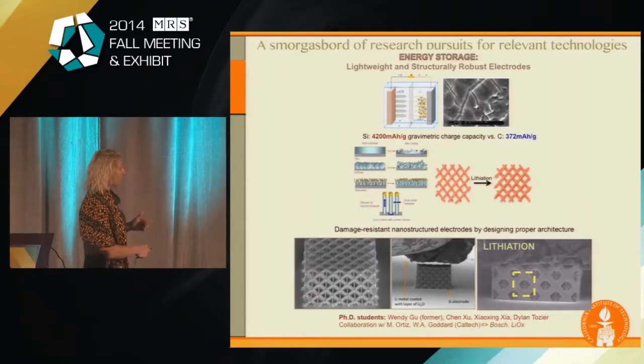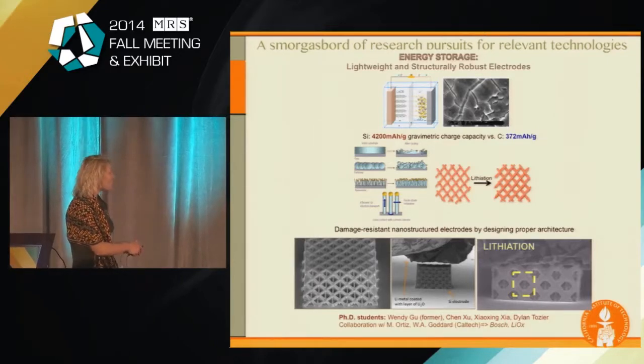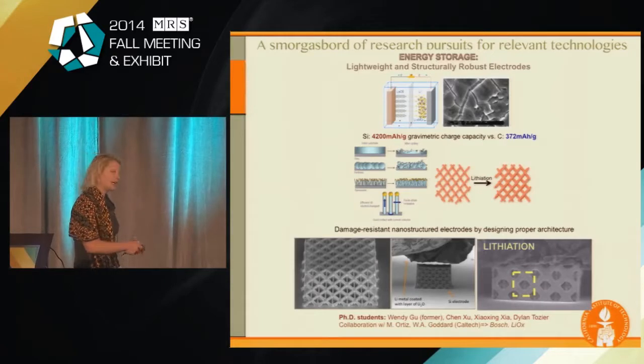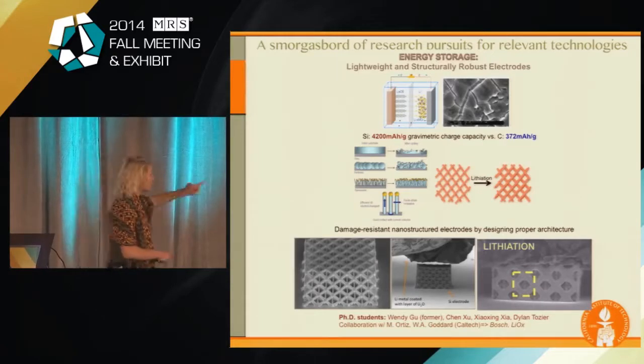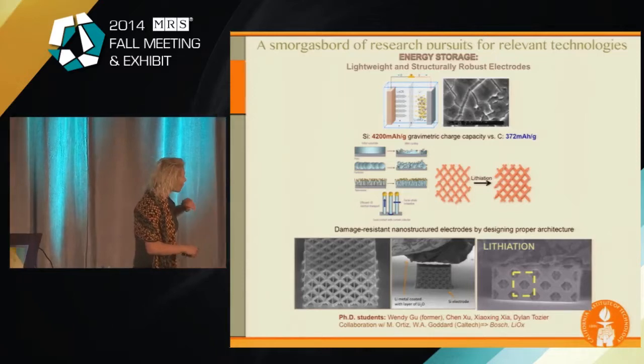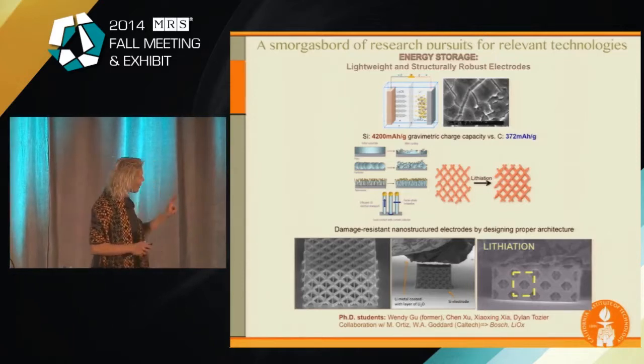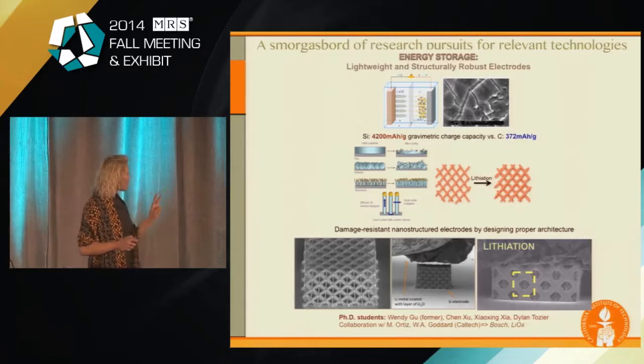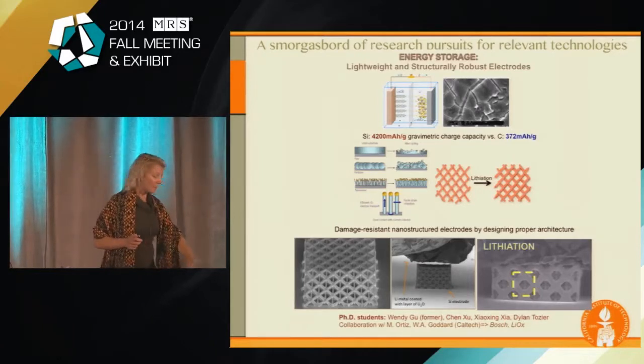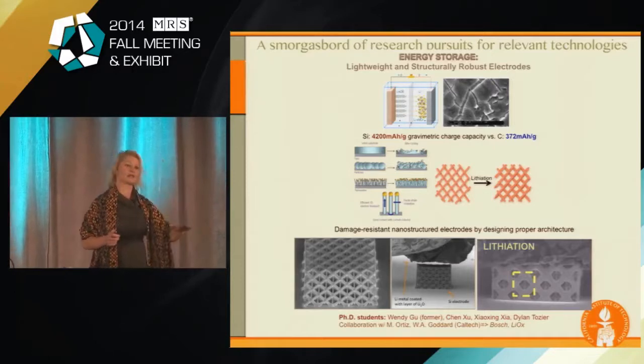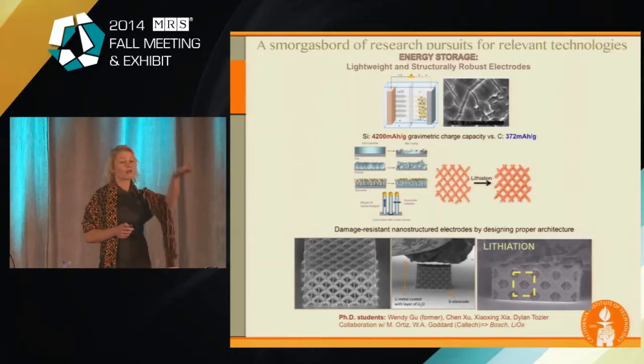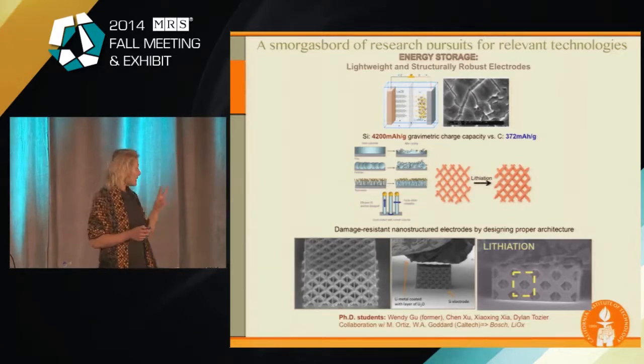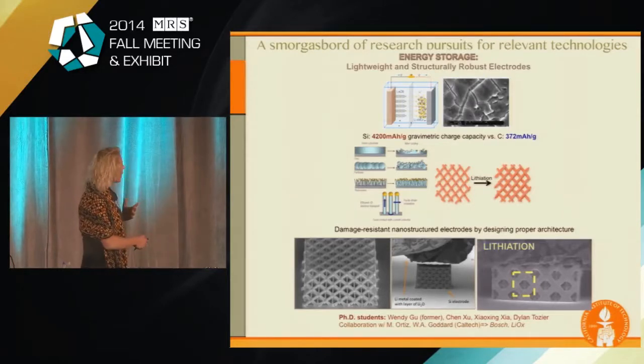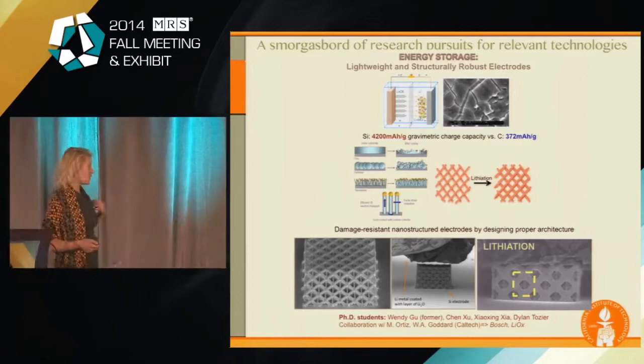There are many groups now, a prominent group, the Cui group at Stanford, that has shown that by nanostructuring silicon, you can bypass that. You can actually store lithium without fracturing. But these are all nanowires, and that's great, but nanowires have two possible shortcomings. When they grow, they saturate at a certain length. So if you were real estate limited, if you only had this much space to work with, you can't grow them infinitely up, right? And the second problem is that they're completely non-resistant to shear. From the structural perspective, these are great, but there are some more improvements that could be done.